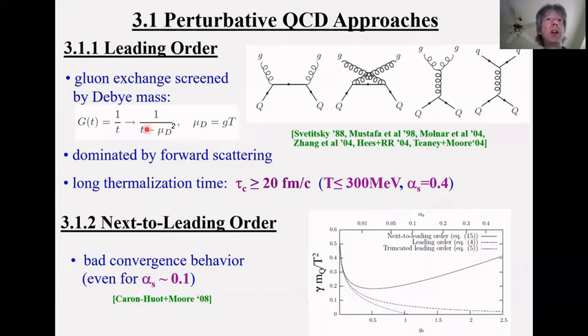Still, because the T is in the denominator, this momentum transfer, which is proportional to the scattering angle, and these diagrams, these T-channel exchange diagrams, the dominant ones, are dominated by forward scattering, and they are not very effective in turning around the angles, in other words, in the thermalization. Therefore a straightforward calculation of the associated thermalization time leads to very large thermalization times, even for charm quarks at relatively high temperature and relatively high coupling constant, of up to 20 fm/c or even more.